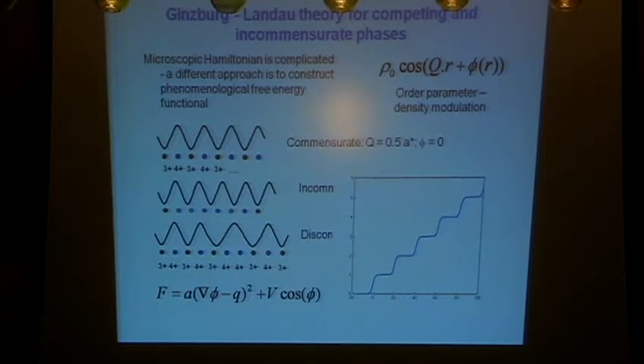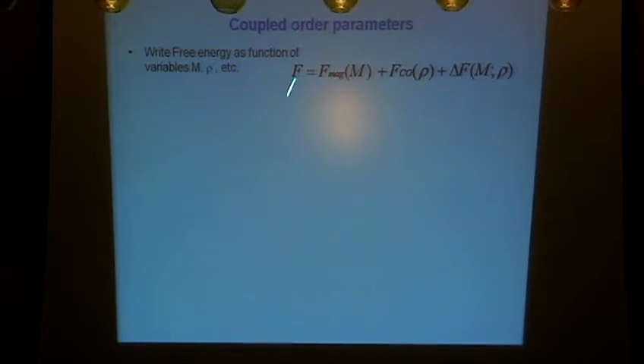But that's been used for a long time to describe models of charge density waves, and it will do quite well as a statistical mechanical model. Now, what happens if I have competing orders? In particular, let's imagine that I have charge order as one ground state, competing with, say, magnetic order in another, and I could write down a Landau theory for both of these two, and then I need some coupling term. And it's the coupling term and the relative minima of these two which determine which phase you get into.